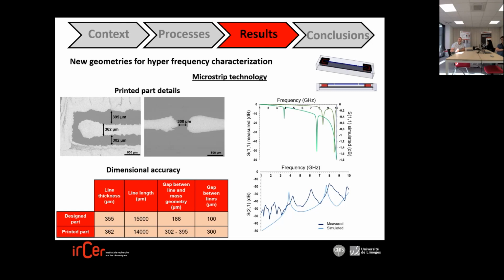Okay, for the first microstrip technology, as you can see, we have got a difference that is presented in the table between the design part and the printed one, especially for the gap between lines and mass geometry. The gap between lines has been explained by many problems we've got, particularly with the accuracy of the robot used, which is not able to make metal shapes with a nozzle lower than 150 micron. So to answer this problem, we have decided to change the robot on the machine and use the same type of device as it has been presented by 3D Ceram in their devices.